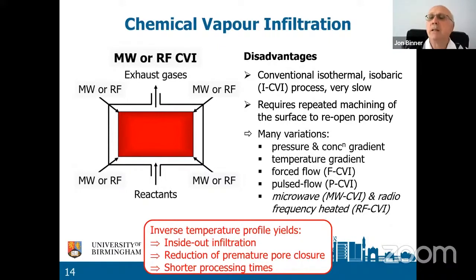What that does is it means that the microwaves heat the silicon carbide fibers, or the radio frequency, the RF, heats the carbon fibers. And what you get is represented in that diagram now, where hopefully you can see that the center of the material, the red is brightest in the middle and darker at the surface. In other words, the center of the body is hotter than the surface. So microwaves heat from the inside out, and so does RF. And that means we now get our deposition in the middle of the body, and therefore we don't get this crust forming at the surface, and therefore we don't have to stop and machine. We can now do it all in one go. So we get much shorter processing times.